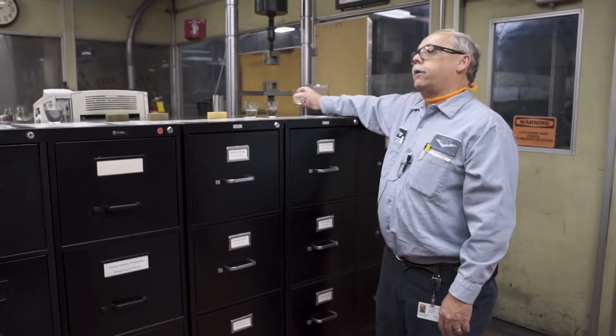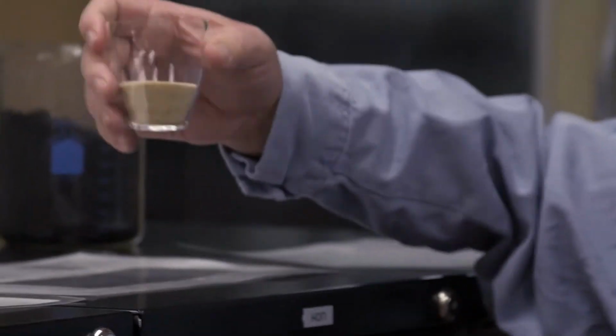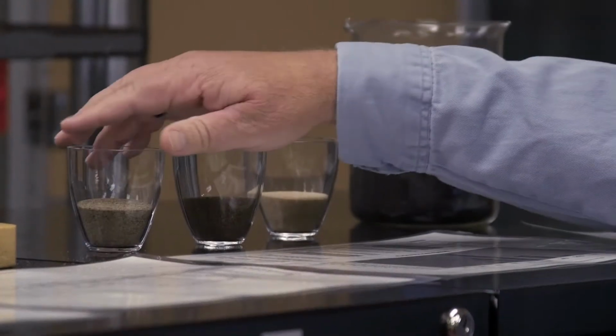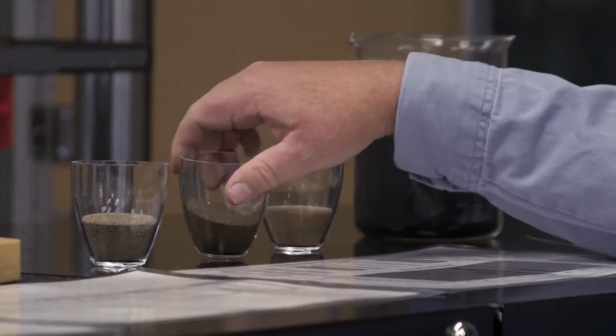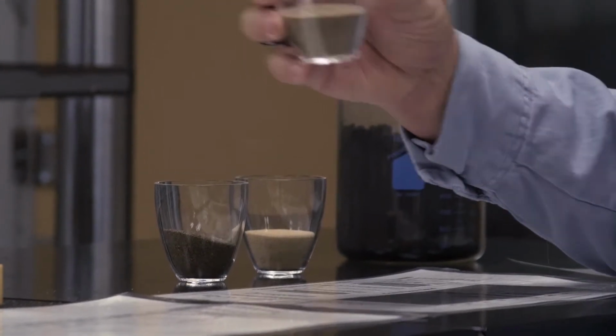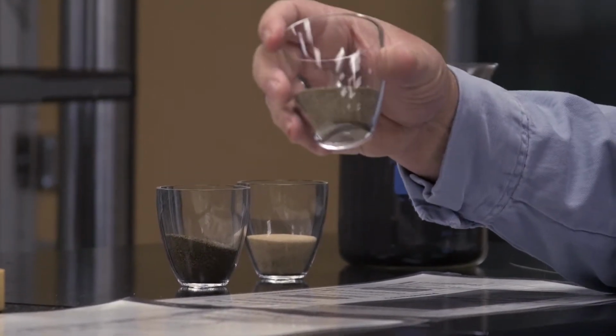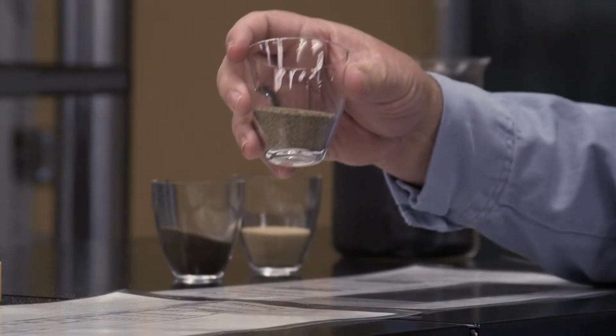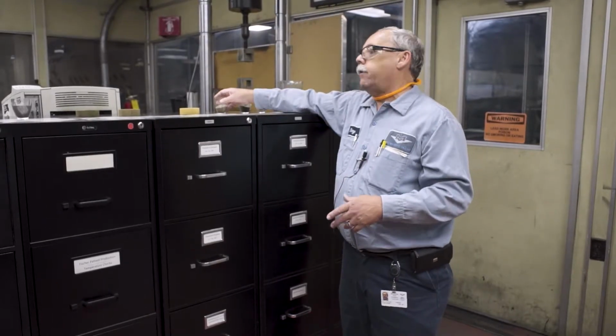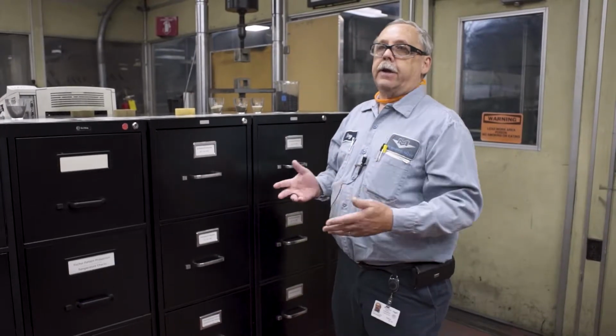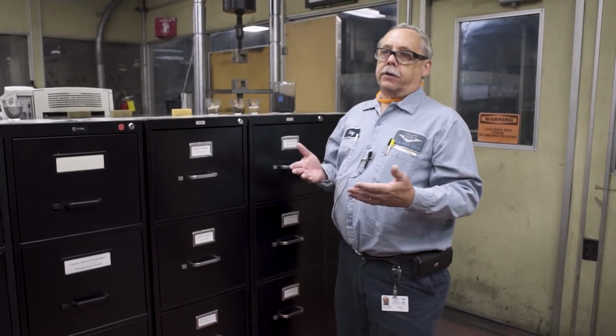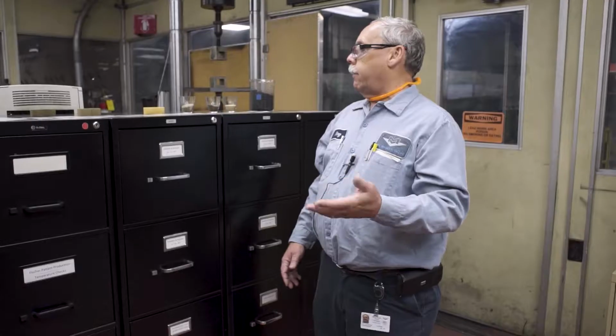We also do an analysis of the grain fineness for the new incoming sand, for the reclaimed sand, and then we mix new sand and reclaimed sand together, and we do an analysis of that also. All of these get an LOI and a grain fineness. The grain fineness is very critical on both the green sand system and the no-bake system, because if we get it too fine, we don't get rid of the gases like I talked about earlier. If we get it too coarse, we get rough casting, a poor finish on our castings. So we got a very critical balance that we have to have on the grain fineness.